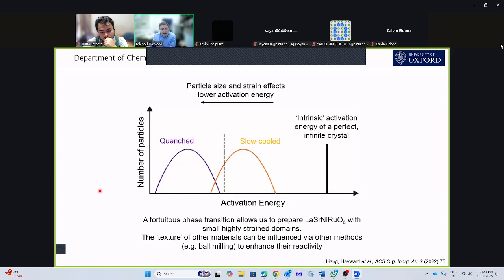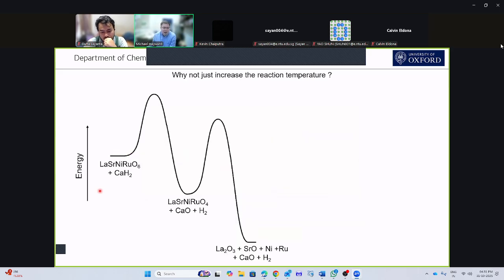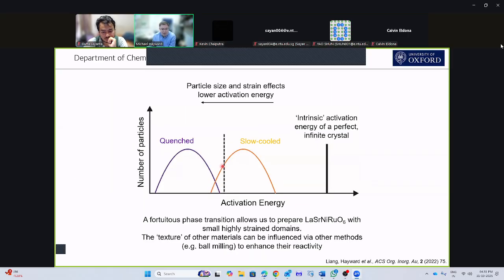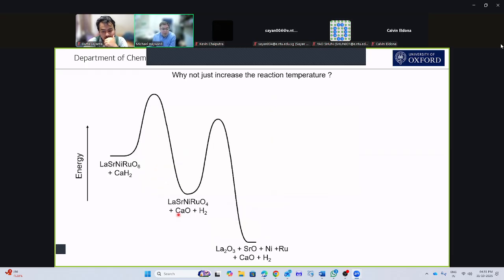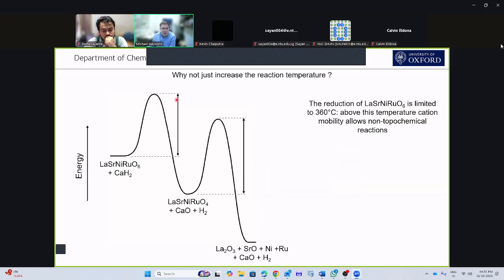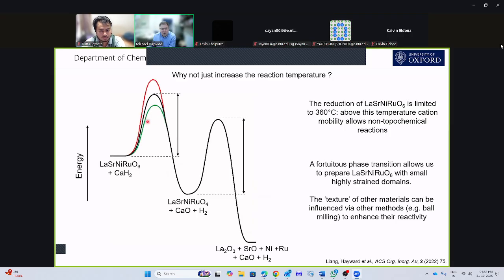Now you might say, well, why don't we just raise the reaction temperature to overcome this activation barrier? So rather than doing the reaction at this temperature here, why don't we do it at this temperature here? Well, generally that's what we would do. But in this system, we can't do that because we have a second reaction that we don't want to do. And this second reaction turns our product phase into the thermodynamic product of the simple binary oxides and the two metals. And what we need to worry about is the relative size of these two activation barriers. And what we find is the size of this second activation barrier fixes the maximum reaction temperature at 360 degrees C. If we go above that temperature, we'll start going over this barrier. So what I actually need to do is modify the size of this barrier in order to get the reaction to work. And that's what we did through quenching. Okay, so that's our first story.